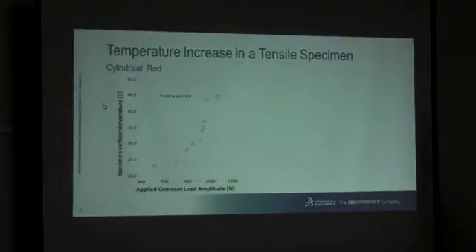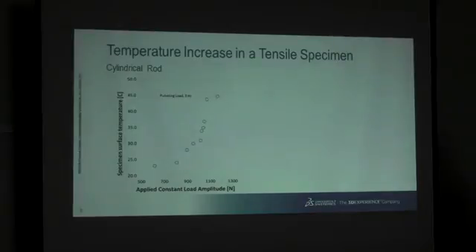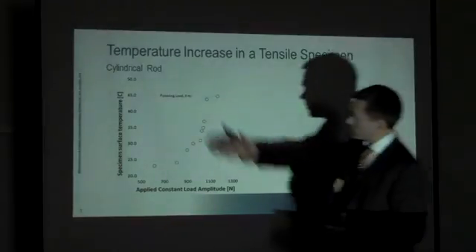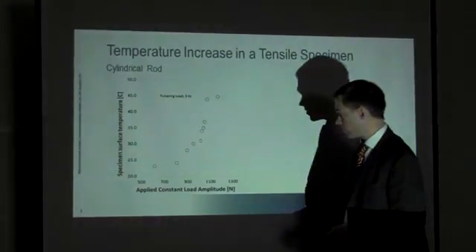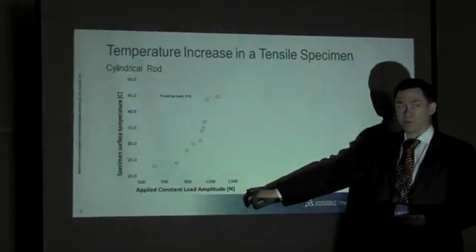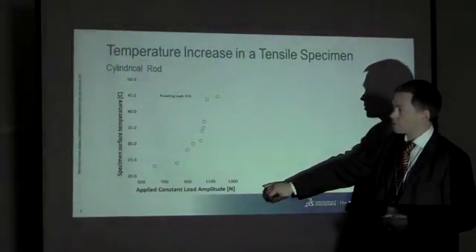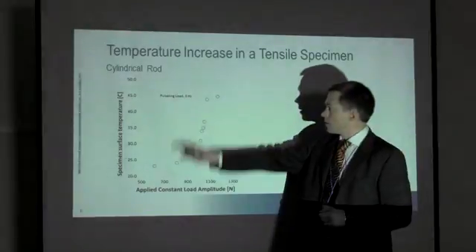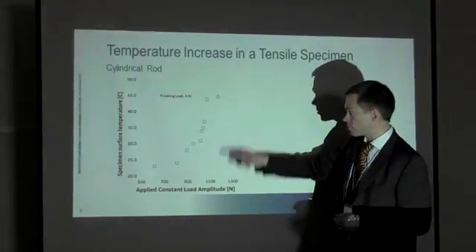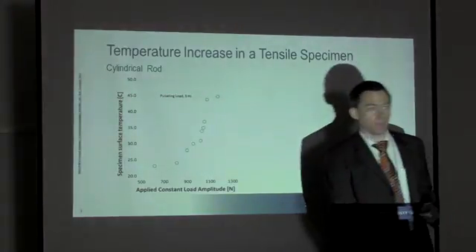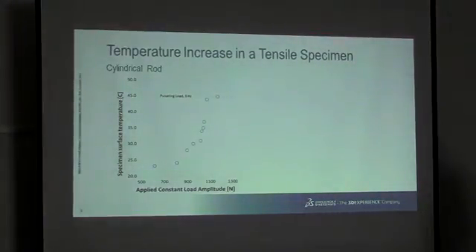Then, another aspect is that you need to look at what's the effect of just increasing the load amplitude. Because frequency is one thing, load is the other. You might actually have a constant frequency, but I can't really see which case that would be, but just in case. So what you see on the vertical axis here is the specimen surface temperature, measured in degrees C, the applied constant load amplitude, so not a realistic case, but for investigative purpose, this serves quite a lot. We apply a pulsating load of 3 Hz, and we see a near exponential increase in the temperature, which is not very good, because that you need to control. You need to understand where it comes from.